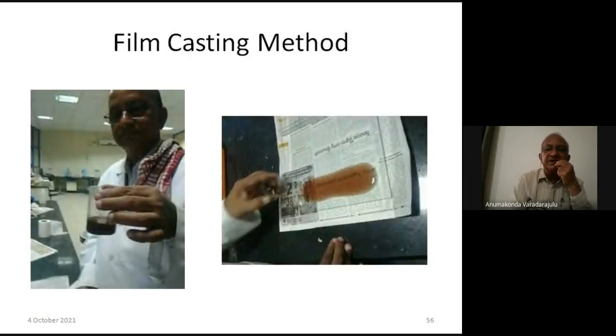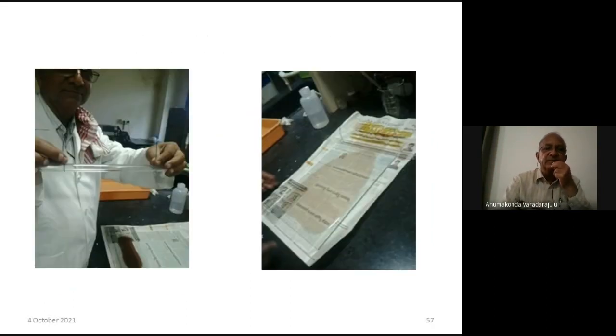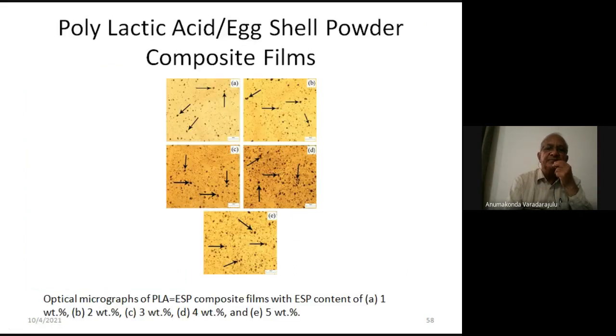So we followed the casting method for the polypropylene carbonate and then polylactic acid, because we don't use the regeneration method but only the film casting method. So we cast the film, give a shape of the film for that composite solution, allow the solvent to dry and peel off the film. So like this we spread it. This is the liquid film, allow it to dry, and after that you can peel off the solid film.